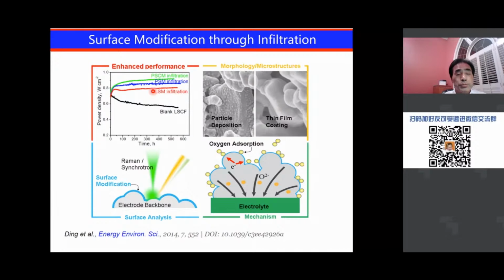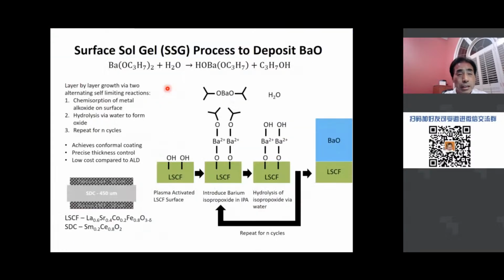And then we can also use the so-called infiltration process to modify porous electrodes. There's a lot of demonstration that by introducing nanoparticles of different catalysts, you can dramatically enhance performance. So here is, for instance, an LSCF blank electrode. By putting down different infiltrations, you can significantly enhance performance. Yeah. And we have also used the so-called surface sol-gel process to deposit different catalysts on porous electrodes. So this gives us very precise control of the chemistry and morphology of coatings in a random porous structure.